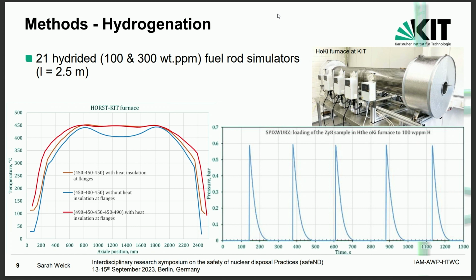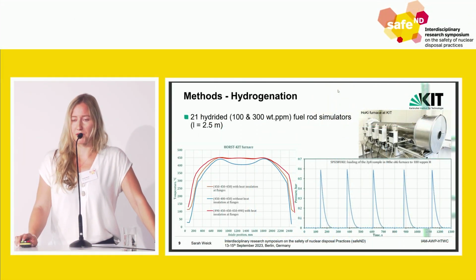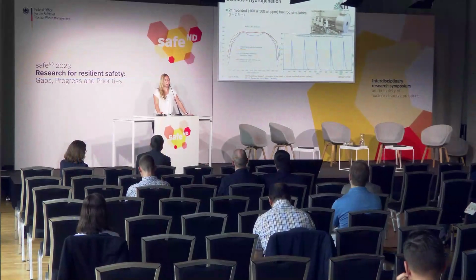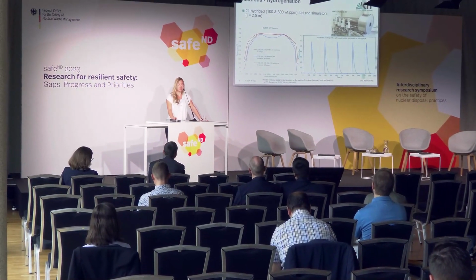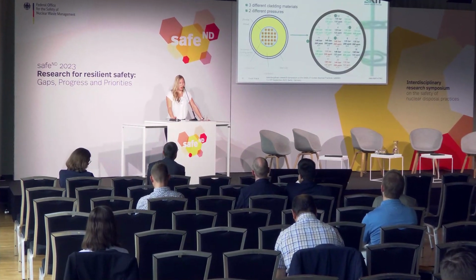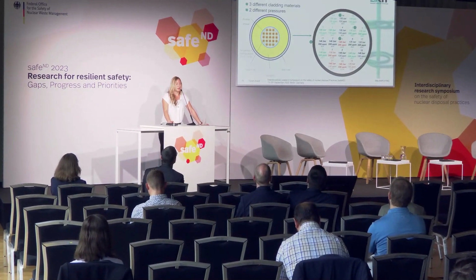With this furnace we also hydrided 21 rods for our quench bundle test, which happens in a way that we always insert some hydrogen gas, but only from the inside of the cladding. From the outside we have some oxygen gas that prevents any hydrogen release, and from within we try to hydrogenate the samples always.